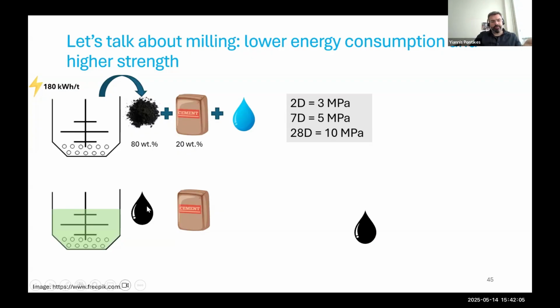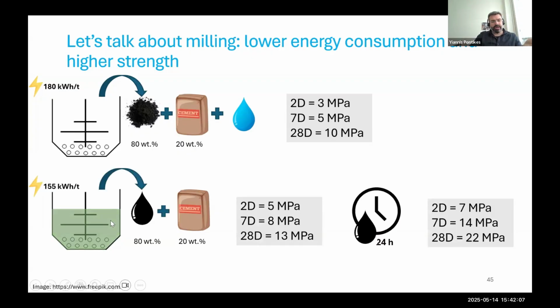What we've done now, we said, okay, let's do it differently. We do the slurry. So you bring the slurry in a liquid with a bit of alkalis. You minimize energy consumption. Then you take the slurry and then you add the cement and the aggregates, and the performance is better. So it means performance better, less energy consumption, 2 thumbs up.